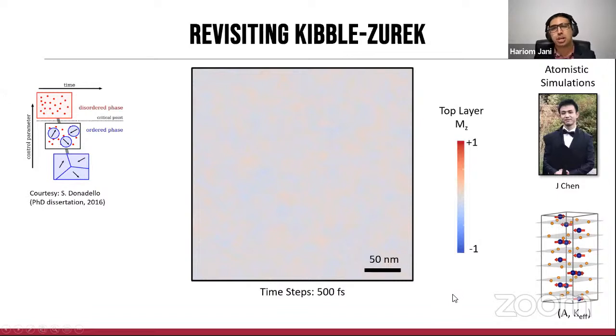Of course, from our experimental data, we know a slightly different version of the Kibble-Zurek transition across the Morin transition allows us to actually have stable objects which are present in the system for very long durations across our experimental time. So there is some kind of gap here, and we suspect this is because of the fact that the terms included in this atomistic calculations do not include aspects which would then enable complete stability. While their dimensionality can be well defined by A and K, perhaps their stability is coming from some other insights, perhaps there is some role of defects here, or the fact that they actually have canting, which is ignored in this very basic set of simulations here.